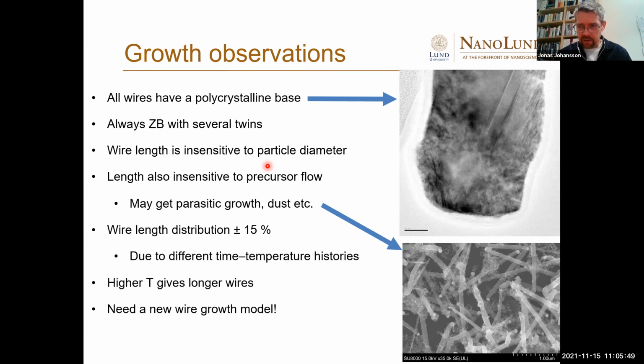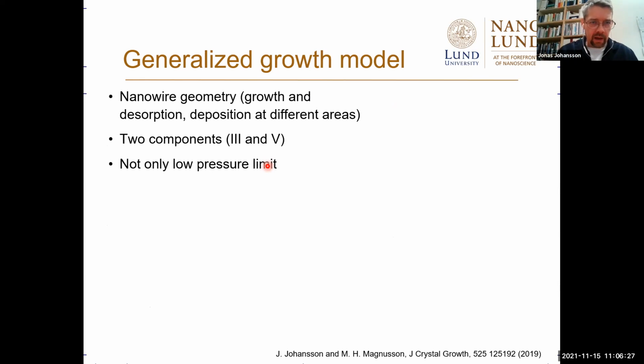So I made a general mass transport model, because the usual mass transport model we have to understand MOVPE growth is derived for the low pressure limit and for a flat surface. So I derived a new model where we can have any pressures. We can also have a saturation in pressure. And I also considered the nanowire geometry. So I consider nanowire geometry, growth and desorption, and deposition of group 3 and group 5 at the different relevant areas. I explicitly considered the 2 components, group 3 and group 5, and not only in the low pressure limit.